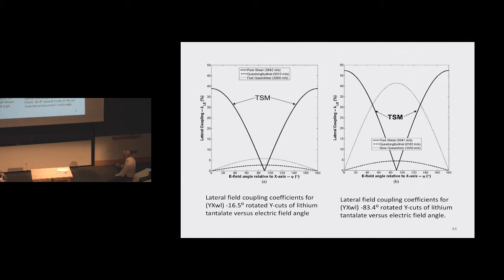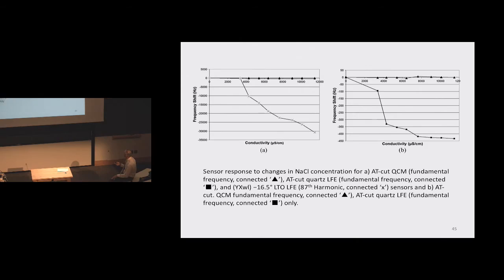We had a choice of choosing this one or that one. We decided to choose this one. You might wonder why. No potential interference with this one, or not as much as might occur in that one. Notice the coupling here, 40, 45, and so forth. For quartz, that coupling percentage was 5 and 6. You're talking about 6 to 7 times more sensitive to the excitation in the case of lithium tantalate.